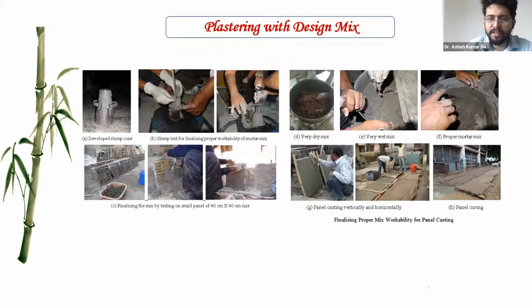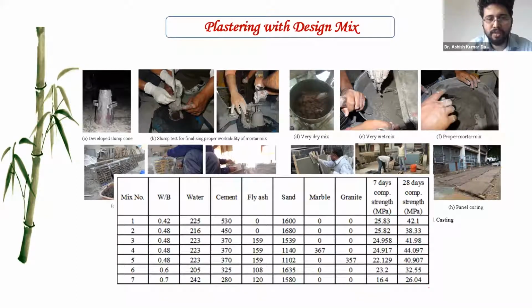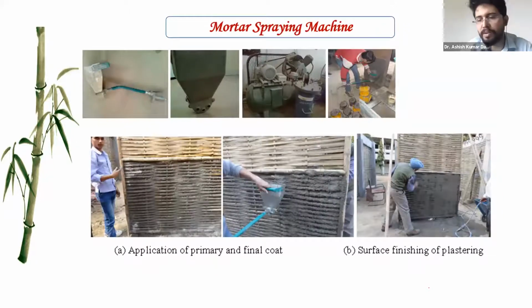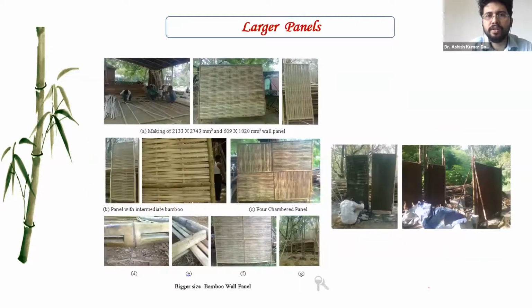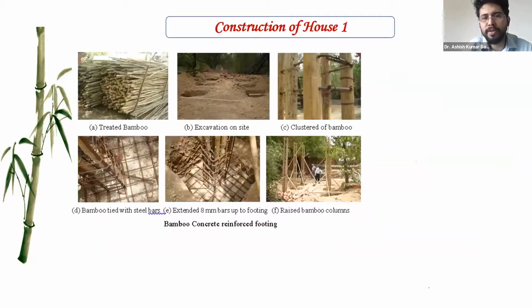So the workability level, the admixture doses, and also this work is now carrying forward, the viscosity and everything. So these are the different water cement ratios we considered, from 0.4 up to 0.7, and casting of the panels was conducted. In the process of casting, the manual casting, now we just consider the machine-based plastering process. So this plastering is using the mortar spraying gun. After this, one house was constructed from the very basic level.